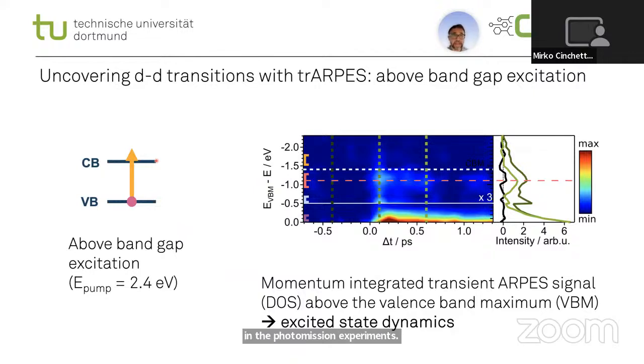Okay, now let me come to the last part, where we did the same experiments, but now exciting the system above the band gap. So here we have much more information in this kind of transient ARPES signal bands. You remember this is basically the transient occupation of the bands. If we integrate over all the energy, we see here that we have at least 3 main features in these line profiles. And this corresponds to various excited states that we are observing in this experiment.